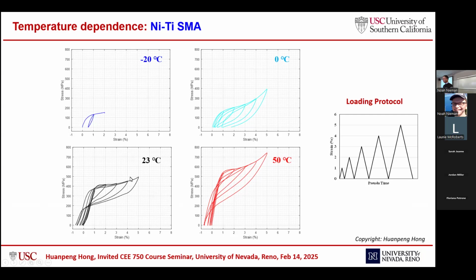And here we see that from room temperature up to 50 Celsius, this material still exhibits good shape recovery capacity. There's almost no positive residual strain. And we see that as the temperature increases, the yield stress of this material increases significantly. And the same, when the temperature decreases, the yield stress also decreases significantly.